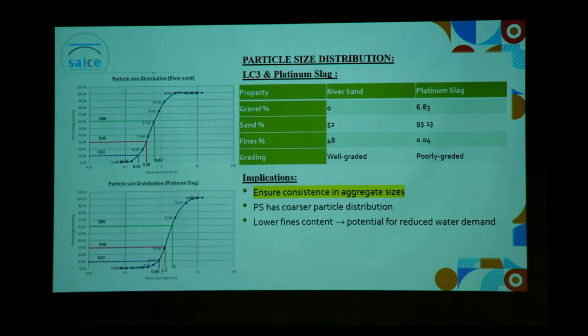And then particle size distribution was also necessary to be done in order to ensure consistency throughout our mixtures when replacing the Portland cement and our river sand and introducing our platinum slag, to ensure that when we're replacing, we're replacing with the same amount of fines and larger aggregates.